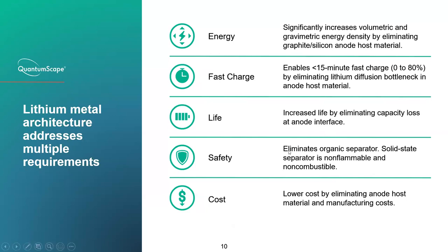Safety, really critically, is improved because we've taken out that liquid electrolyte and replaced it with something that is very, very stable. In fact, I didn't talk too much about this yet, but the way we make this ceramic separator is through a heat treatment process at very high temperature. So it's stable to over 1,000 degrees Celsius. So even in the most extreme conditions, it's not going to react. And then cost can be improved because we actually have less material. We don't have to make the anode and there's less manufacturing at the same time.